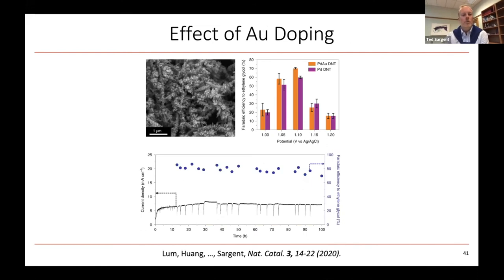And so they pursued the development of nanowires shown in the top left here that were both palladium and also palladium gold, and found that they could indeed improve the Faradaic efficiency to ethylene glycol through this doped gold palladium nanomaterial strategy. Now, you'll also note that the current densities they were operating at were in the kind of 5 milliamp range, which is very far from the industrial range that we were interested in.